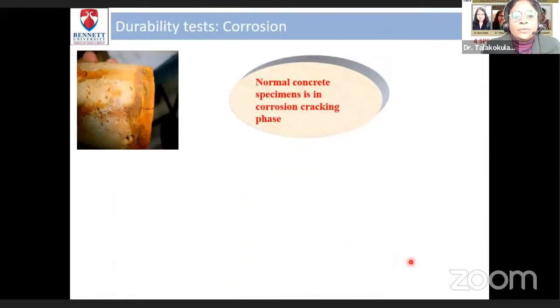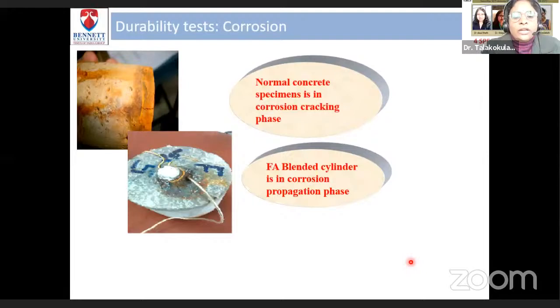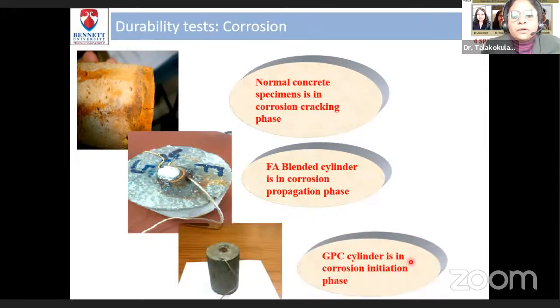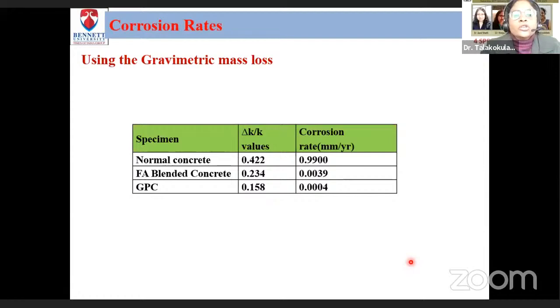And if you look into the durability aspects, the corrosion experiments conducted in the laboratory found that after around 120 days of accelerated corrosion exposure, normal concrete specimen was found to be in the cracking phase, and the fly ash blended concrete specimen was found to be in the propagation state, which is the second phase of corrosion. And in geopolymer concrete, there were no signs of corrosion products on the surface, and they were found to be in just the first phase of corrosion, which is the corrosion initiation phase. So from this, we understand that the geopolymer concrete has better durability than the other conventional concretes. And also the corrosion rate of GPC is very low when compared to the normal and the blended concrete.